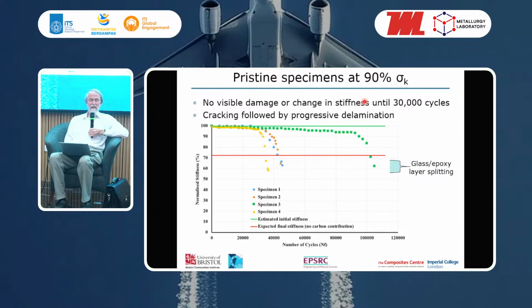So what's happening here is, because at 90% of that knee point strain we're getting quite close to the carbon failure stress, some of the fibers were already broken, and when we cycle it in fatigue, you can get some damage growing. But not initially, so it goes up to quite a large number of cycles before that damage starts, and then it fails progressively.